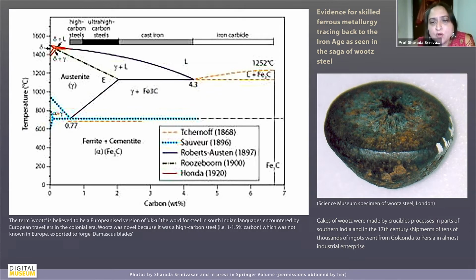But the interesting aspect of the wootz steel was that it had a carbon content of about 1.5% carbon in the iron. And actually, to keep adding carbon to iron, in Europe, they really followed what was called a solid state cementation process, where of course when you heat the iron itself in very reducing conditions, some carbon gets in. But what was the novelty about wootz was that they had discovered a way in which you can carburize wrought iron in crucibles, packing it with carbonaceous materials and so on, so that the carbon could get in and you get this ultra high carbon steel composition, about 1.5%. And this steel had very good properties where it had a very good cutting edge and very good tensile strength and so on, which was why it was much sought after.